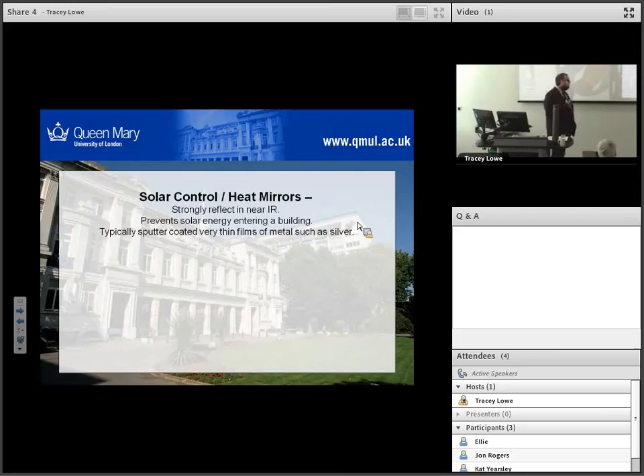Okay, so what existing products are there? Well, there are solar control heat mirrors. These are going to strongly reflect in this near infrared region, so your heat gain's not going to go into your building. It'll stop your building getting hot, and that's great. Typically, they're made of very thin films of silver or metal alloys, and they're produced by sputtering. Now, the problem with that, of course, is that PVD deposited films don't tend to have the lifetimes that we would like for windows in the building.